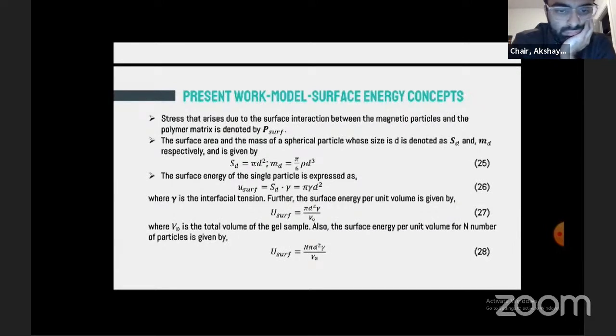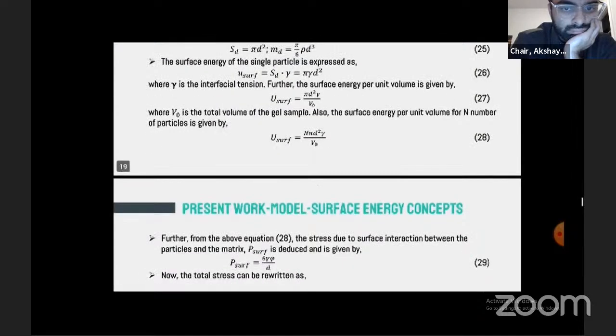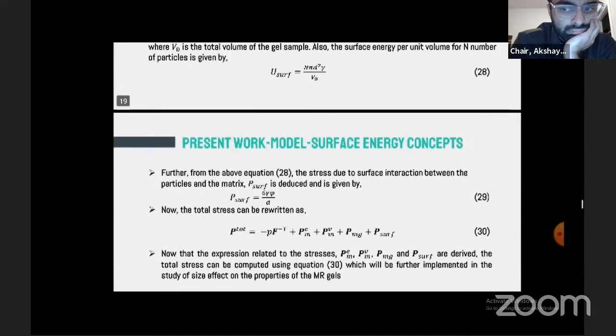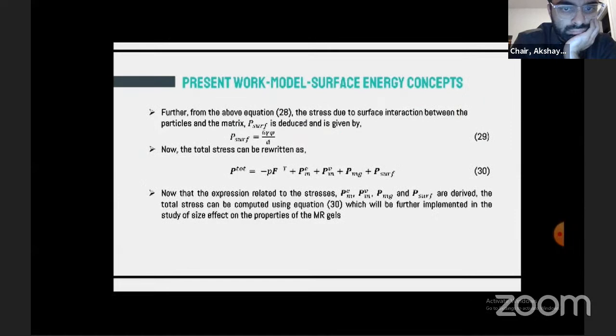And the single particle surface energy is expressed easily in equation 26, where gamma denotes the interfacial tension. The surface energy per unit volume is rewritten for n number of particles as shown in equation 28. Further, using the above equation, the stress due to the surface interaction between the particles and the matrix is deduced and is given by equation 29.